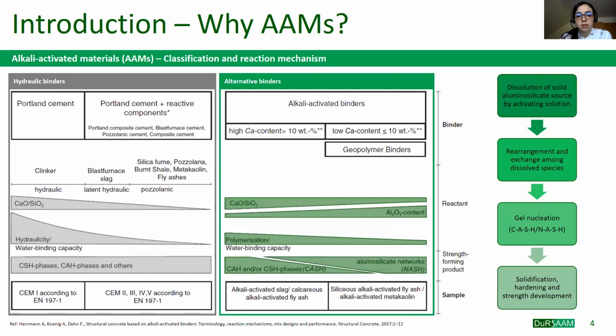Supplementary cementitious materials have been widely used as cement replacement in traditional concrete to improve both mechanical and durability performance, and also to reduce the environmental impact related to cement production. However, if combined with an alkaline solution, these aluminosilicate-rich binders can react, forming a new construction material with similar performance compared to OPC concrete. Depending on the chemical composition of these binders and mainly on the calcium content, two different